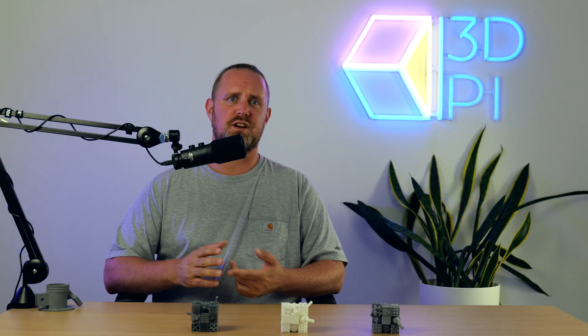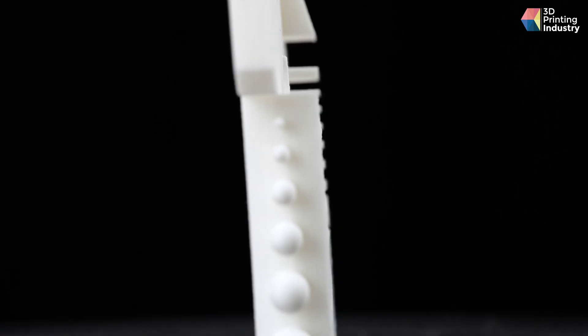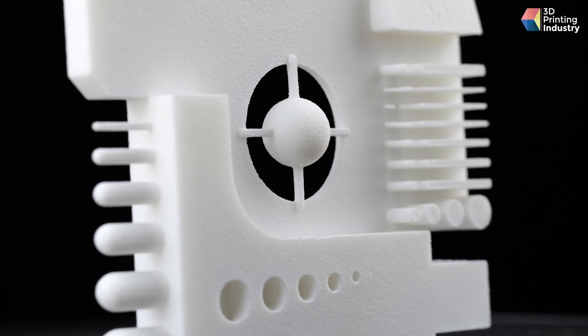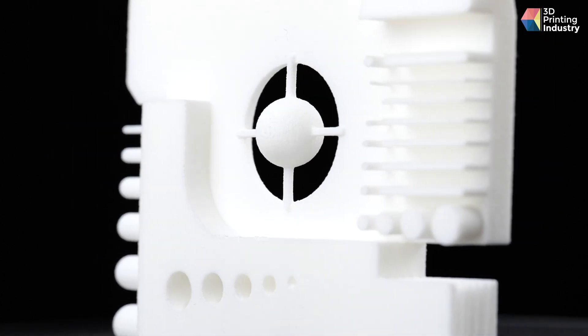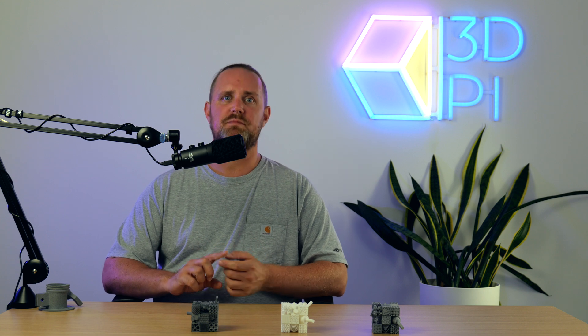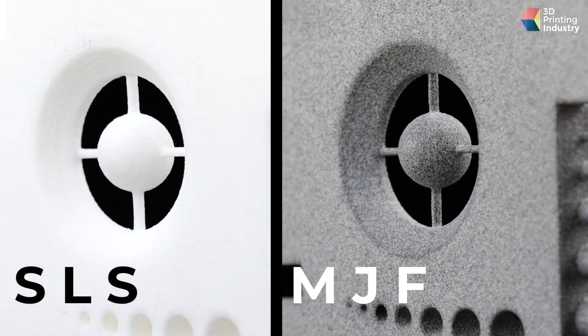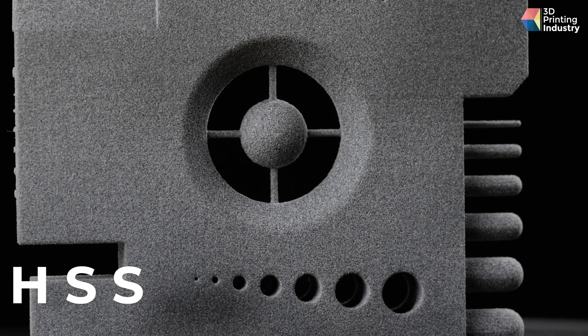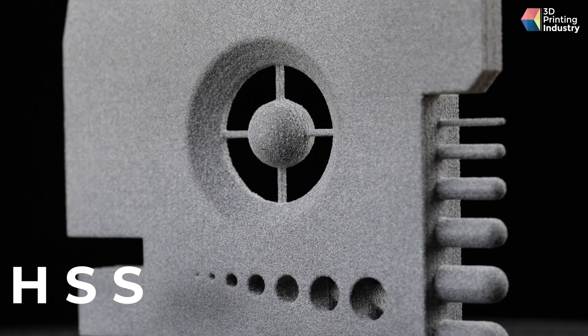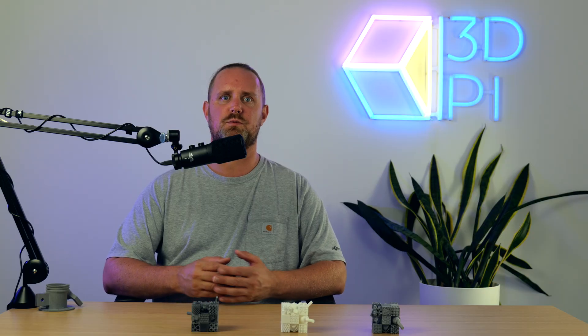From the 3D printed benchmarking models, the HSS variant had the finest geometric grooves and clearest writing — a testament to the process and suggesting that grain size is more important than DPI when it comes to detail resolution. The SLS part was the only one to successfully fabricate all the towers, with HSS and MJF missing the thinnest spike. Interestingly, the holes on MJF and SLS builds were printed as true circles, whereas the HSS process yielded holes that were closer to ovals. However, HSS once again delivered the finest edges and sharpest corners, while SLS and MJF were noticeably blunter.